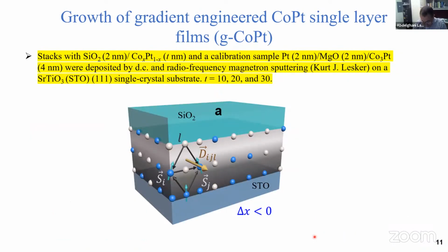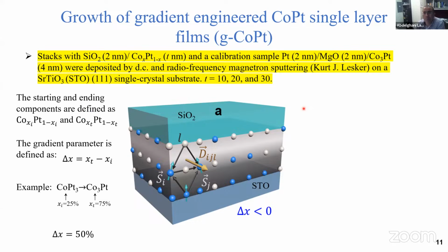So the system we study in particular was grown by our collaborator, Qingsheng Chen, at the National University of Singapore. They grew this cobalt platinum. We vary the thickness, in this case 10, 20, 30 nanometers, on a substrate. Also, we use a 2 nanometer cap just to coat the film to prevent any oxidation. This is done using DC magnetron sputtering. In principle, this is done on a single crystal substrate.